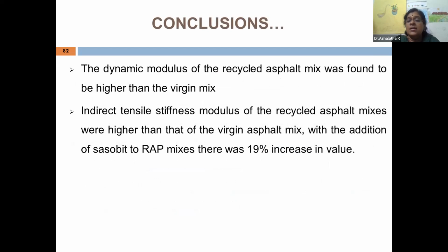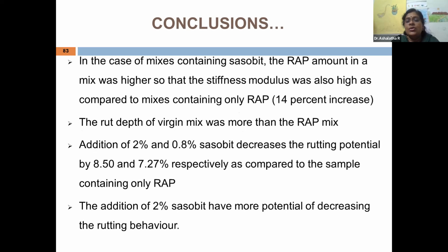And the dynamic modulus of the recycled asphalt mix was found to be higher than the virgin mix. And the indirect tensile stiffness modulus of the recycled asphalt mix was higher than that of the virgin asphalt mix. With the addition of sasobit to RAP mixes, there was a 19% increase in the value. In the case of mixes containing sasobit, the RAP amount in the mix was higher, so the stiffness modulus was also high as compared to the mixes containing only RAP.